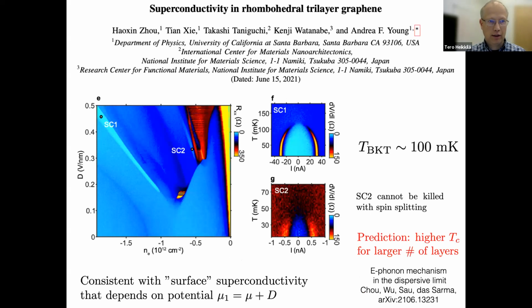So this is the experiment that was published. Actually, this is already now in Nature. This was in Nature this September, so I should have actually added the reference. I think it was in my earlier slide. So basically what they did here was to take this rhombohedral 3-layer graphene, and they studied the resistance as a function of the charge density and as a function of chemical potential difference between the layers, which is basically an electric field inside the graphene.